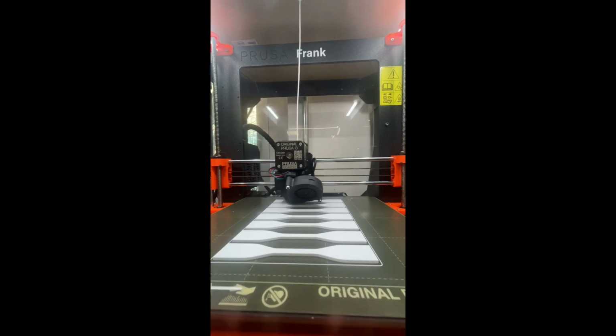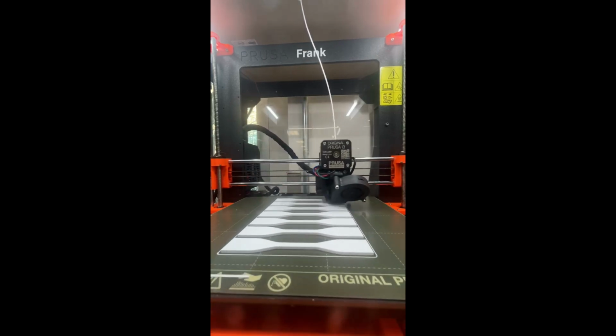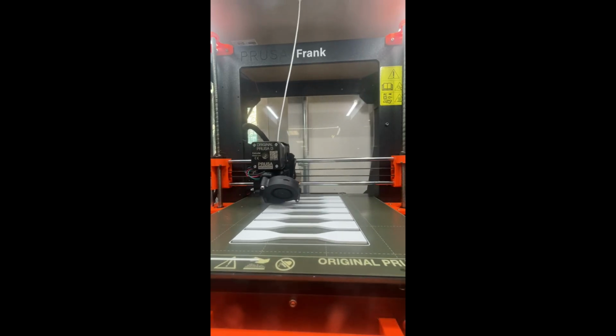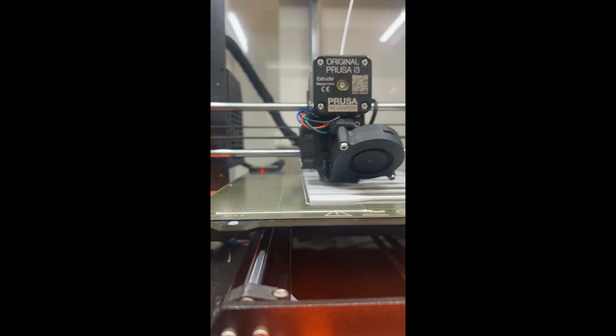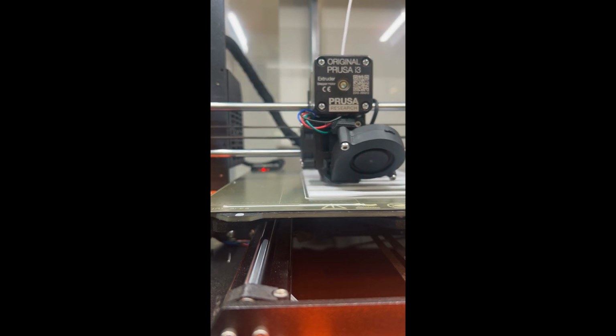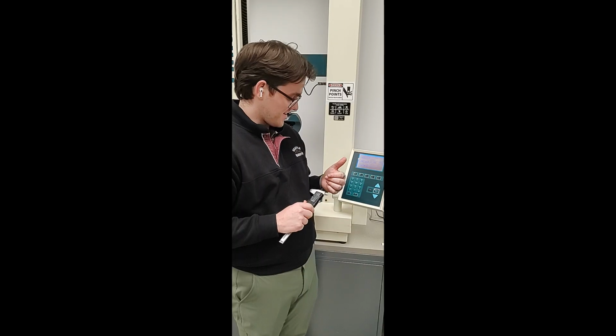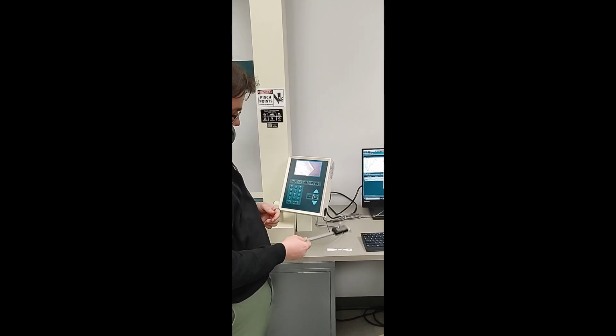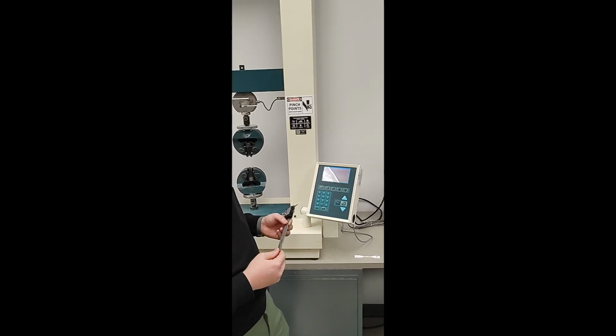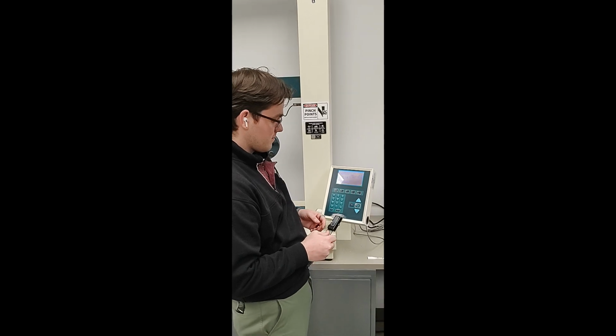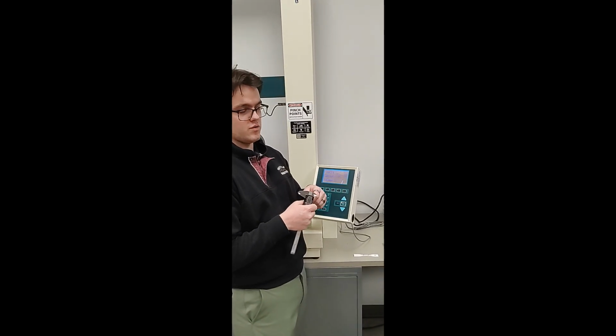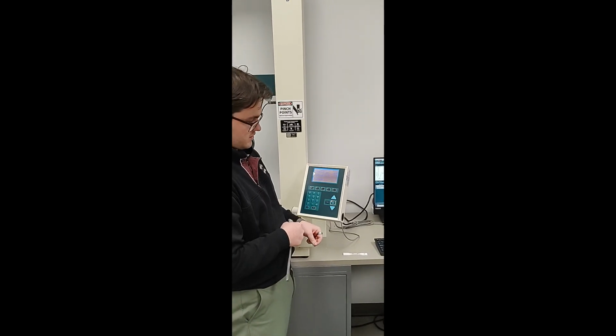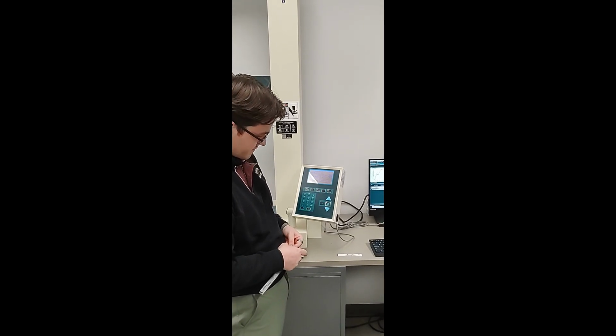For the 10% infill specimen, the Young's modulus is 633 megapascal. That is going to be the lowest value, because when the infill goes up to 100, the Young's modulus is going to reach around 3000. I think that the higher the percentage of infill goes, the more elastic it'll be, because there's more material there to resist just this brittle break that we have.